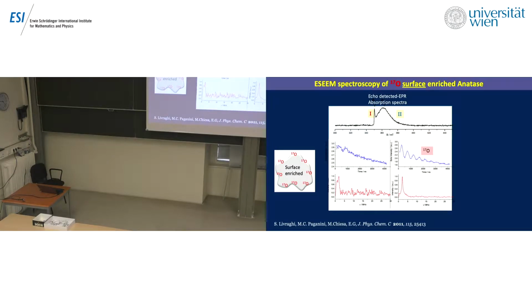In this case, we use the technique that is electron spin echo envelope modulation, no technicality. The spectrum is the one you have seen in the form of derivative. Now this is the integral form, but it's the same. This is species 1 narrow, and this is species 2 broad and featureless. But what you observe when you point your field here or your field here is a different modulation of oxygen. Here there is the trace of oxygen 17. If you do the Fourier transform of this, you obtain the Larmor frequency of oxygen 17. So this species 2 is in interaction with oxygen 17, so it is at the surface, because we have enriched the surface only. In the other case, there is some trace of far away oxygen 17, and so the narrow species is in the bulk and far away from the surface, not interacting directly with oxygen 17.